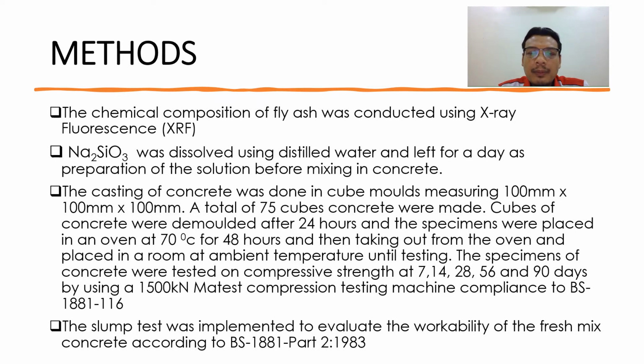Cubes of concrete were demolded after 24 hours and the specimens were placed in an oven at 70 degrees Celsius for 48 hours, and then taken out from the oven and placed in a room at ambient temperature until testing. The specimens of the concrete were tested on compressive strength at 7, 14, 28, 56 and 90 days by using a 1500 kN Matest compression testing machine compliant with BS 1881-116.